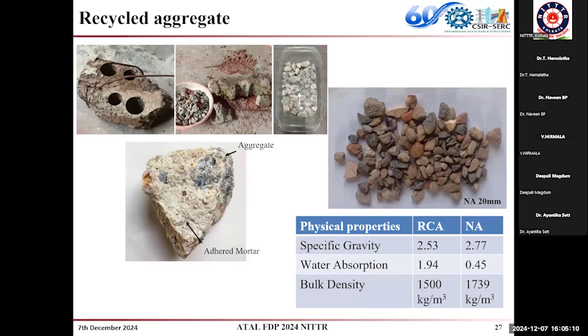Here I have shown how recycled aggregate looks and how we make it. This is from old concrete. It is crushed and we remove the coarse aggregate from this old concrete. The problem with recycled aggregate is that when we crush and remove it, it is very difficult to remove the mortar adhered to the aggregate. This creates an interfacial transition zone. So when we use recycled aggregate, it may have two interfacial transition zones: one between the aggregate and the old mortar, and, when this aggregate is used in new mortar, another between the already existing mortar and the new mortar.